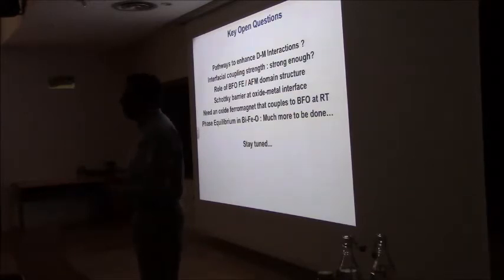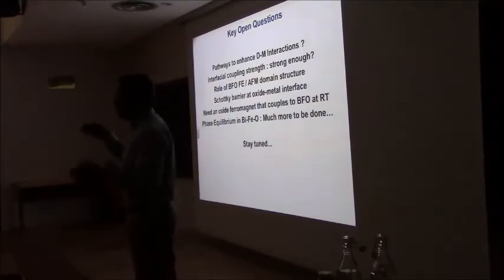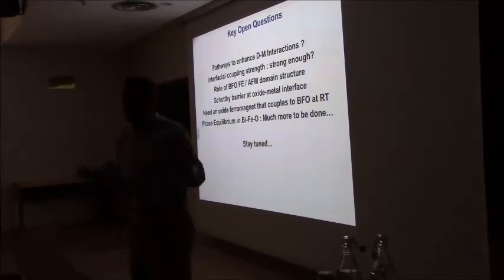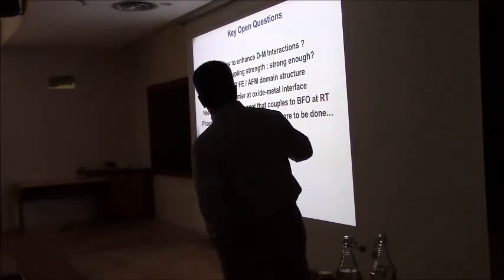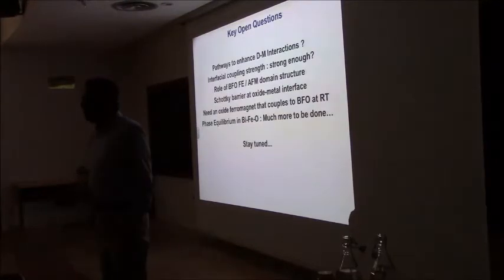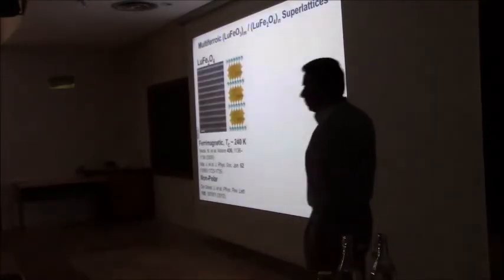Spinels are not very good because of very large lattice mismatch of the perovskites. They start to facet. Spinels love to facet. Therefore, the surface quality is no good. We have a lot of defects at the interface. That's a big challenge. If we can get a ferromagnet, we're now working, trying to see if there are other ferromagnets that we can look at this kind of problem. So that's an important requirement. So we need an oxide ferromagnet that couples to BFO at room temperature. I think the whole business of phase equilibrium in bismuth ferrite, a lot of things to be done there. And so we'll go on.